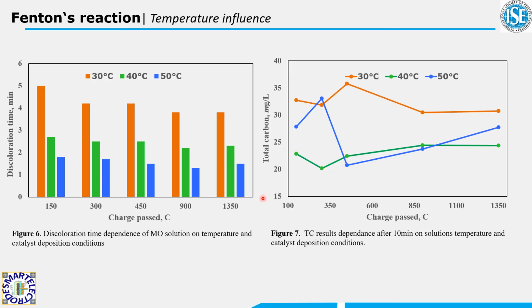We have also investigated what effects the solution's temperature has on the discoloration and mineralization rates. The discoloration rate, as expected, increases with the increase of the temperature. The best result we managed to achieve was discoloration of 100 milliliters of solution containing 100 milligrams per liter methyl orange in 90 seconds. We have also looked at how the temperature influences mineralization efficiency. And as we can see, the best result was achieved using 40 degrees Celsius, where in 10 minutes we managed to mineralize around 30% of all the organic material in the solution.